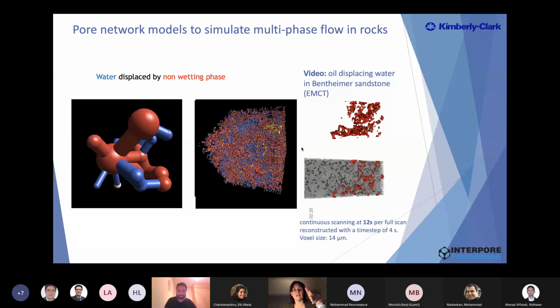And so what you see on the left is modeled on this stone, and on the right you see how oil is displacing water in the same sandstone as a function of time. So I will repeat again, you see that oil is coming from the right to the left, also similar to the model, and the model is based on the CT information here, and so you can start to validate those models.